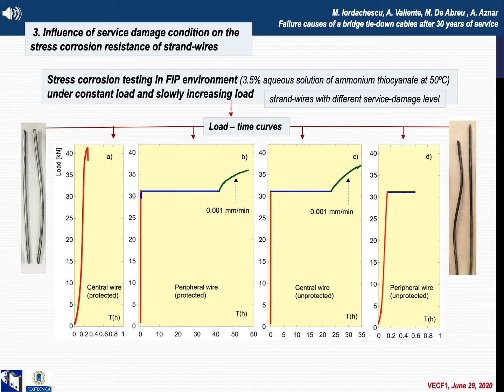As illustrated in figure C, the central wire, although exposed to the environment action, wasn't significantly altered in the 30 years of service, its stress corrosion resistance being comparable to that of the protected wire given in figure B. In contrast, the peripheral wire from the unprotected strand section barely survives 0.5 hours in the FIP solution when loaded to 80% of its resistant capacity. This poor resistance to stress corrosion cracking was attributed to the existence of previous service damage which favored its rapid rupture by hydrogen uptake during testing.